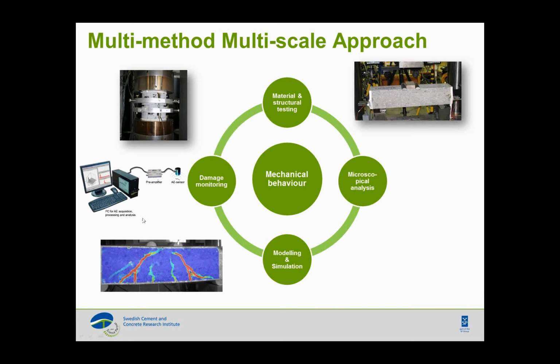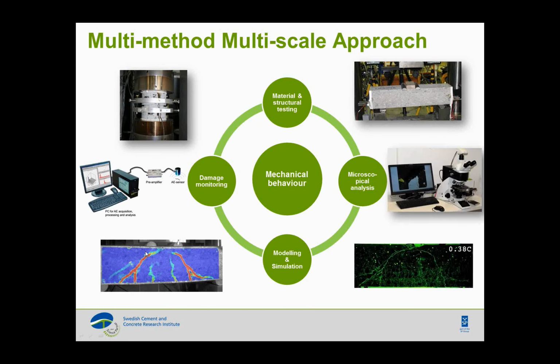When the damage is going on the structure, or when you actually test specimens taken from reality. So in this case we use digital image correlation to look at the strain localization. We also use acoustic emission to capture where the most fracture in our specimen takes place. We also look into microscopical analysis, try to understand what is the mechanism that triggers the damage in the first place. That helps if you want to prevent your damage. That helps a lot, but also to understand how the damage influences the structural behavior. You have to have an understanding of the mechanism itself.